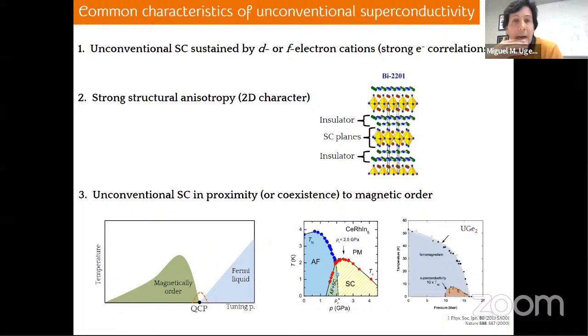And finally, another common characteristic of these unconventional superconductors is that superconductivity usually develops near magnetic phases. In general, they usually develop around something called quantum critical points, here at the onset of a phase transition of a magnetically ordered phase, a second order phase transition. So it's the perfect place for superconductivity to develop, in a region where the magnetic fluctuations are significant. Here I show you a couple of examples of these two heavy fermion compounds. In this particular one, superconductivity is developing near the antiferromagnetic dome.